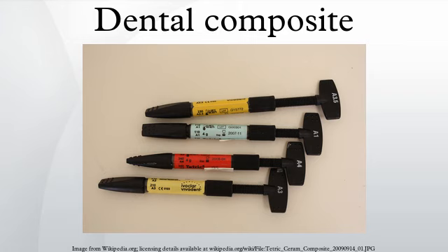In a study of 1,748 restorations, the risk of secondary caries in the composite group was 3.5 times the risk of secondary caries in the amalgam group. Good dental hygiene and regular checkups can mitigate this disadvantage. Most current microhybrid and nanohybrid composites have a polymerization shrinkage that ranges from 2% to 3.5%.